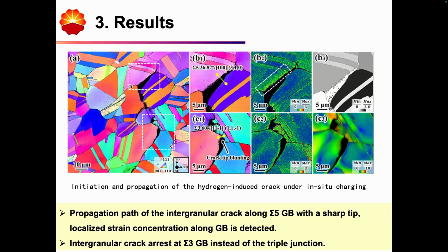And why it propagates - one reason is about the sigma 5 grain boundary, and also from the Taylor factor calculation, we can see that cooperative deformation happens.